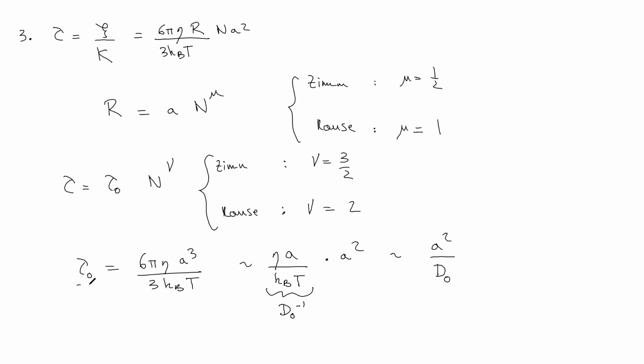So it's really the relaxation of a monomer. This is the time scale of the relaxation of the monomer. And what we are saying is that there is an amplification factor. There is this reference, which is the relaxation of the monomer, but for the full chain of size N, the relaxation is much longer. It grows with a certain power of N being equal to 2 or 3/2, depending on the type of description or hydrodynamics we consider.